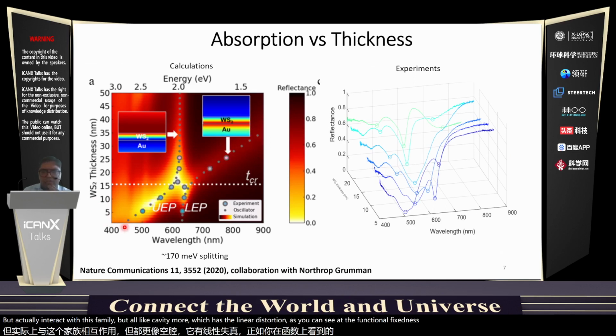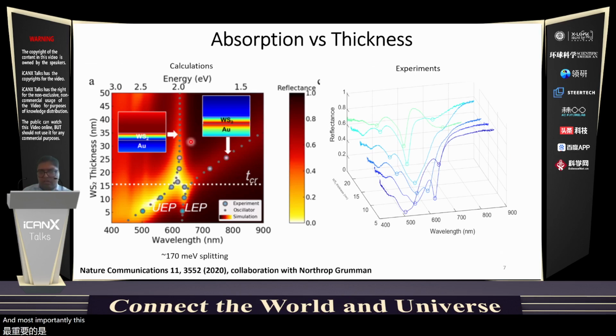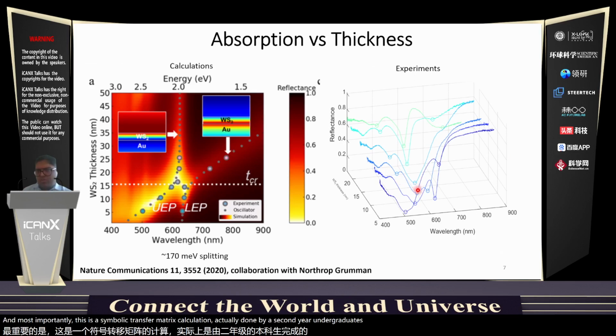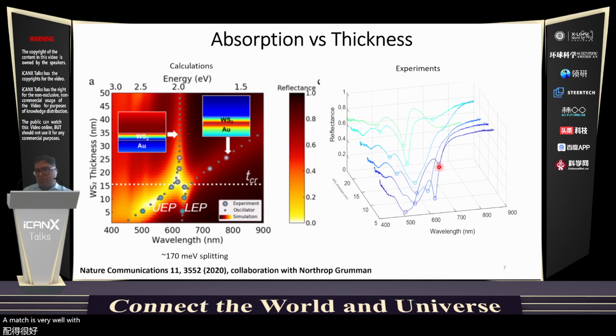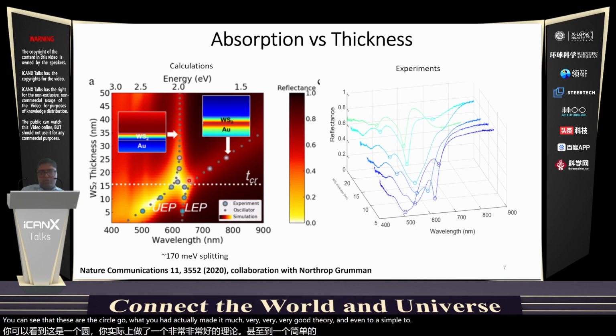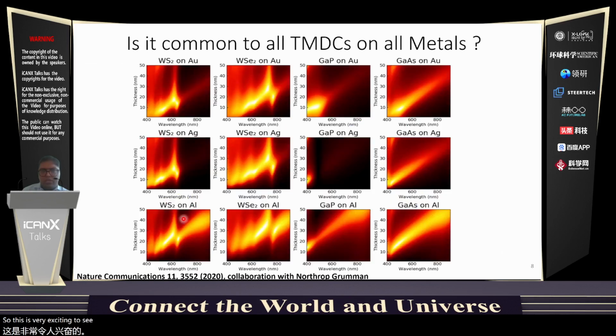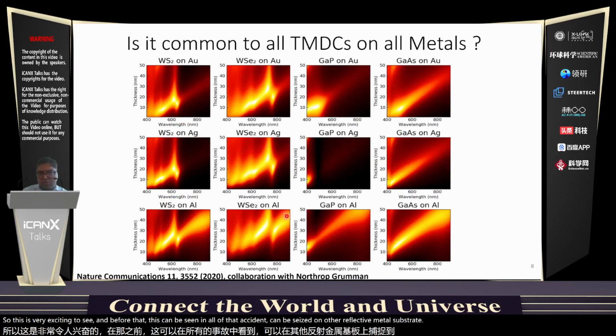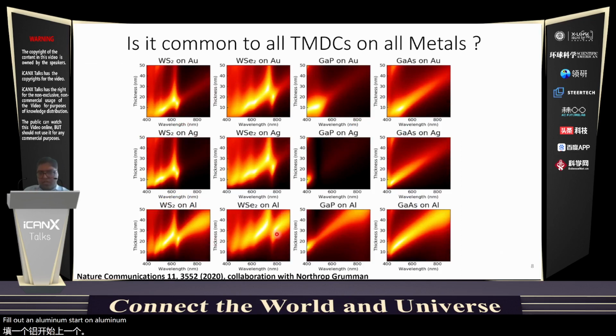of thickness. And most importantly, this simple transfer matrix calculation, actually done by a second-year undergraduate student, matches very well with experiments. The points taken from experiments, when put on this graph, are the circles over here. They match very, very well with theory and even with a simple two-coupled oscillator model, which are these dashed lines. All right, so this was very exciting to see. And we saw that this can be seen in all other excitonic TMDCs on other reflective metal substrates, such as even silver and aluminum. On aluminum, it is particularly strong, as you can see.